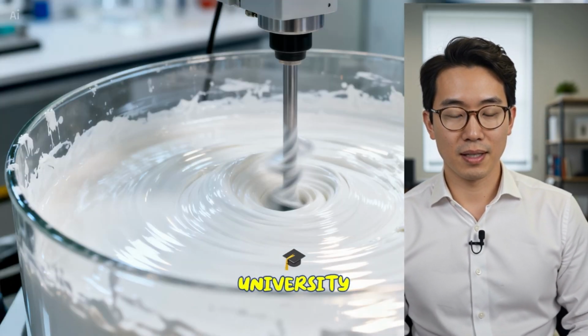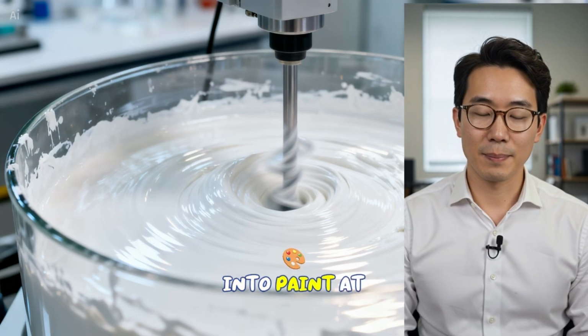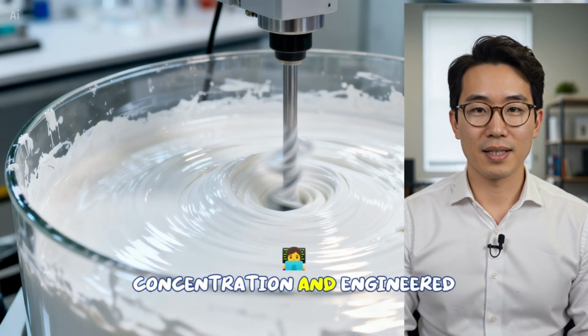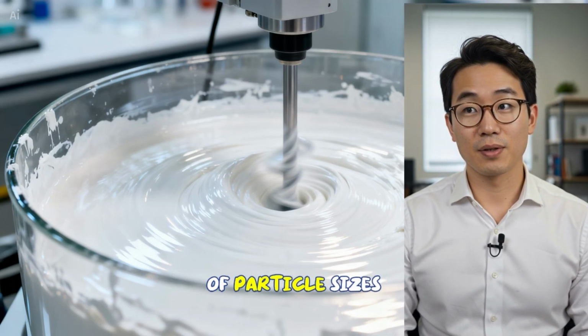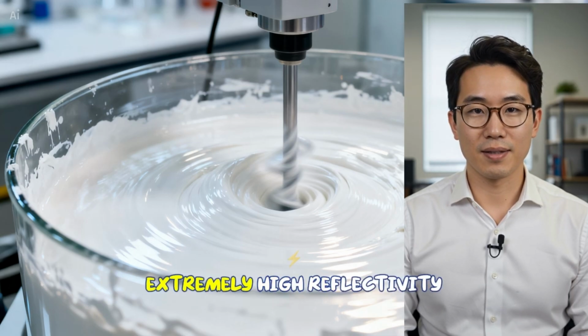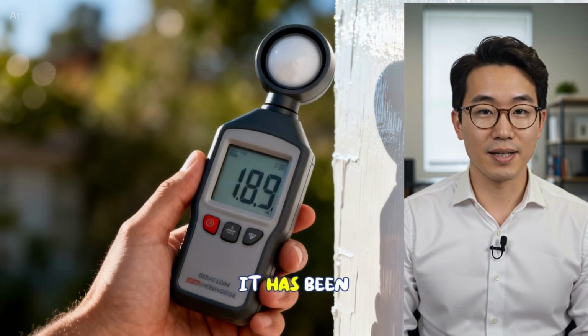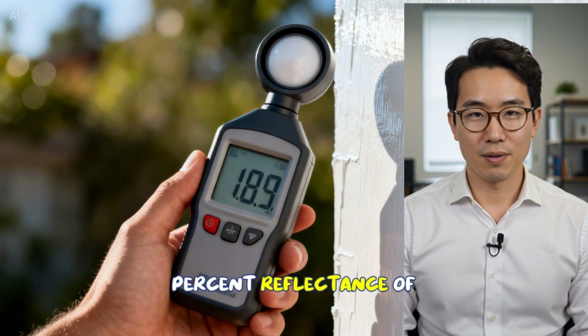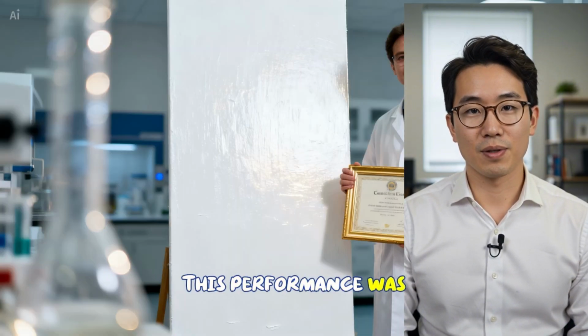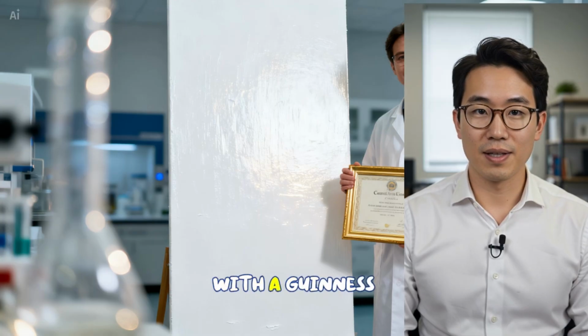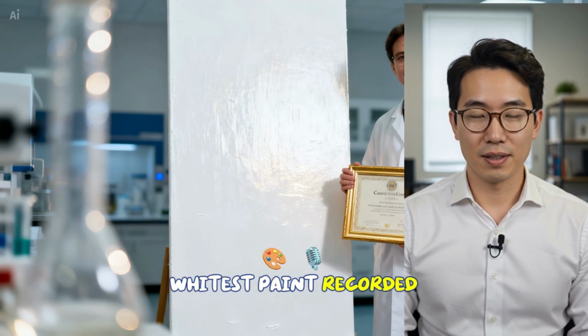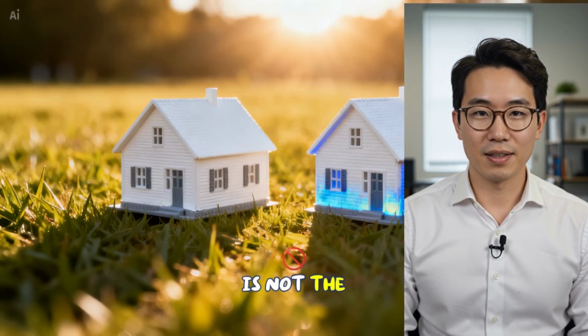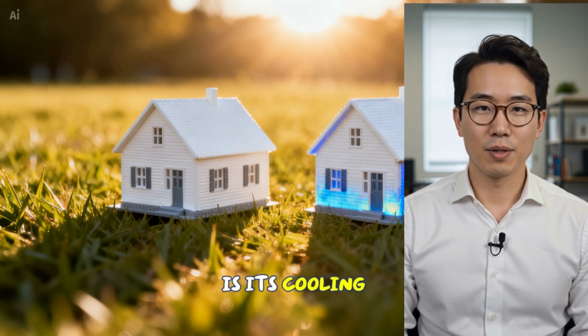Researchers at Purdue University found that when this powder is incorporated into paint at very high concentration and engineered with a wide distribution of particle sizes, the resulting coating achieves extremely high reflectivity. It has been measured at about 98% reflectance of sunlight. This performance was so high that it was recognized with a Guinness World Record as the whitest paint recorded. But the significance is not the record itself. The key factor is its cooling behavior.